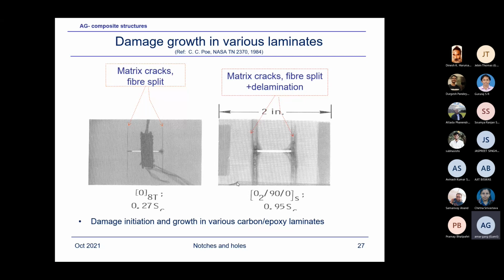So now this is not my work. This is from NASA, Christopher Poe's work, which I just take to demonstrate. Suppose you have a 0 unidirectional layup, then what happens? You will expect this is the original crack. And when you are loading this, you would find that the crack cannot propagate this way. There are fibers, so it has to break the fibers. The simplest path is because there is a shear stress existing right near the crack tip. And this shear stress causes the split. So the crack will propagate along the load line. This is a load line along this one. And as you can see, the crack is propagating along the load line.